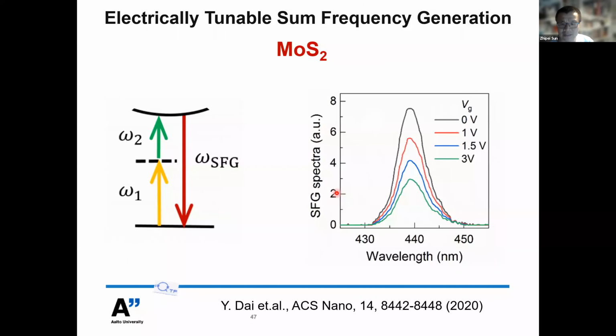We also demonstrate electrically tunable sum frequency generation inside MoS2 in the same devices, as long as the input or the generated wavelength is resonant to the exciton wavelength. If we look at the physics behind, this is pretty similar to the traditional single-resonance or double-resonance cavities for nonlinear optics. But here we don't use a cavity; we use the bound electron and hole pairs with the exciton resonance.